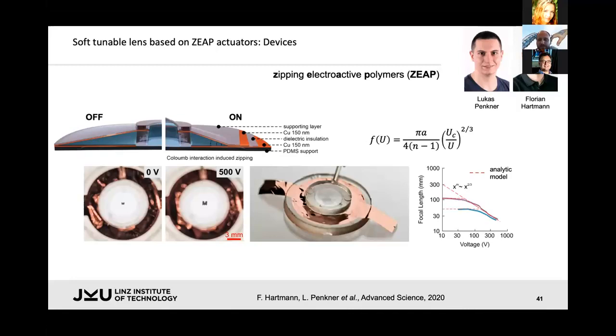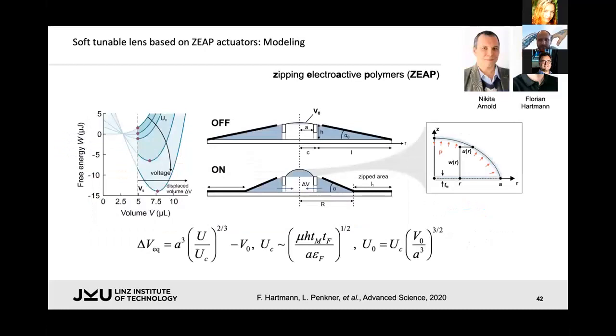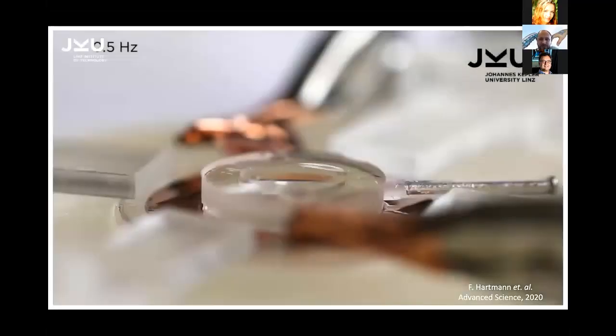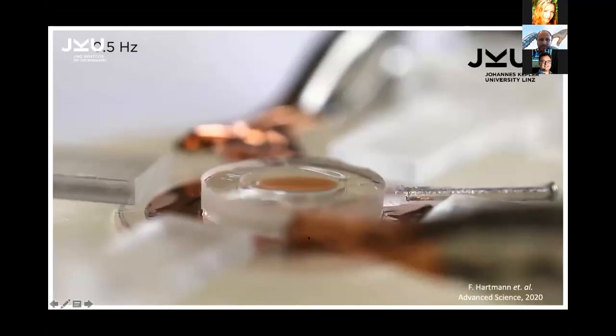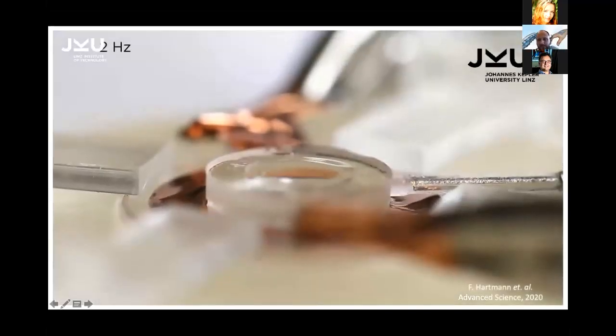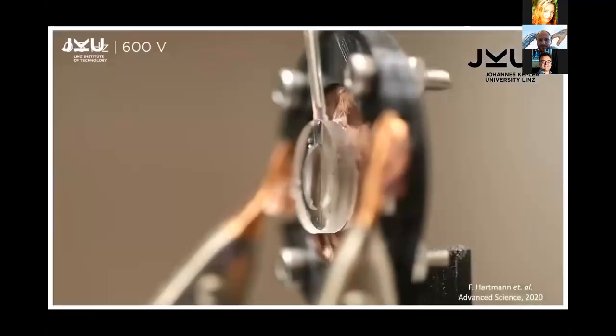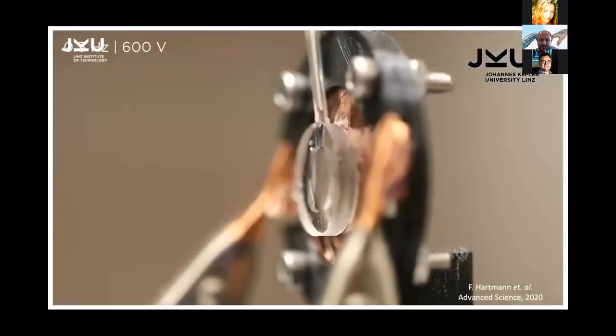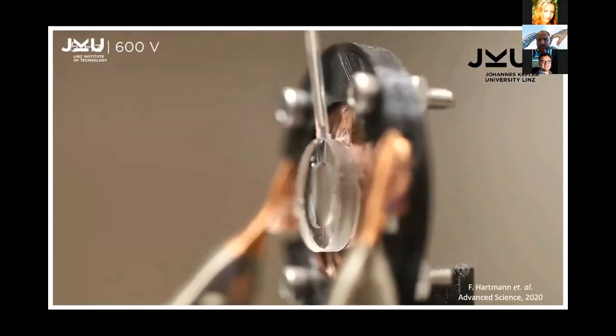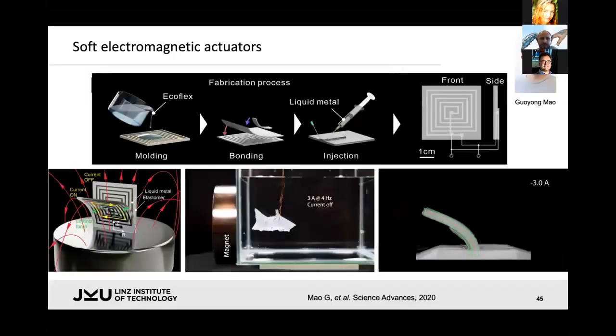Our contribution here is a focus tunable lens. So by the same principle, we displace the liquid in the outer ring. Via the pumping mechanism, we change the curvature of a bubble in the middle, and we change the focal length. Again, we have a complete theoretical understanding of this, but I will not go into detail. I'm just going to show you how these microactuators work. So the electric field that you need here is just a couple 100 volts, and we know how to reduce it even further. And for this, we get quite a significant change in the focal length. But I'm very, very certain that this type of mechanisms can also be used to inflate and unroll other types of pneumatically electrically coupled actuators.